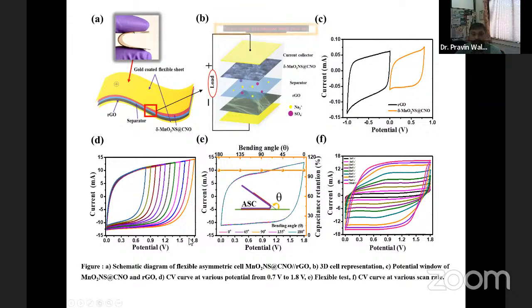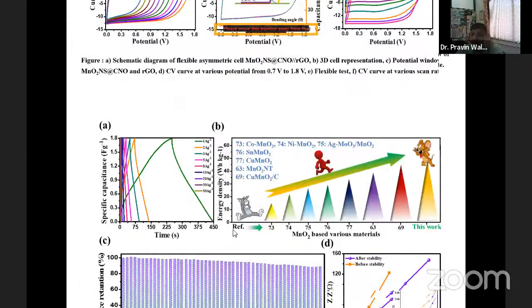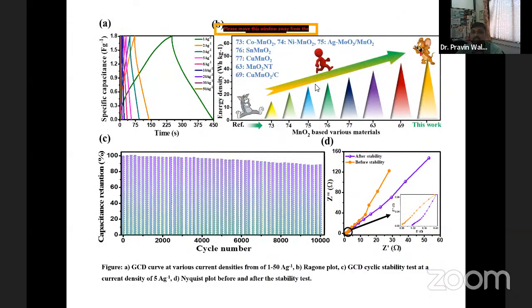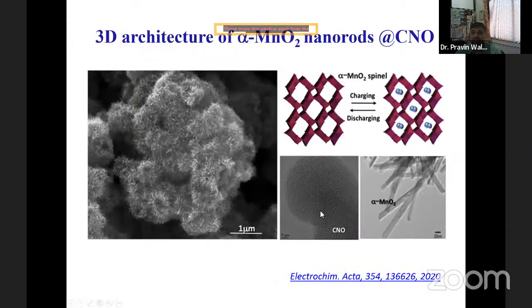So the voltage is very high. The moment you increase the operating voltage, you can increase the energy density of this device. And this is the increment, this is the result of that particular material as compared to the existing material. We can find beautiful material development by just using the CNO as well as MnO2 sheets altogether, and it has up to 10,000 cycles.